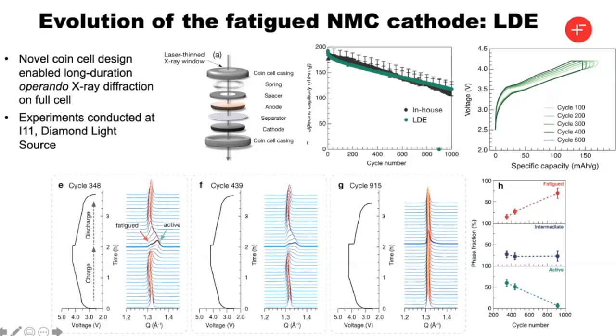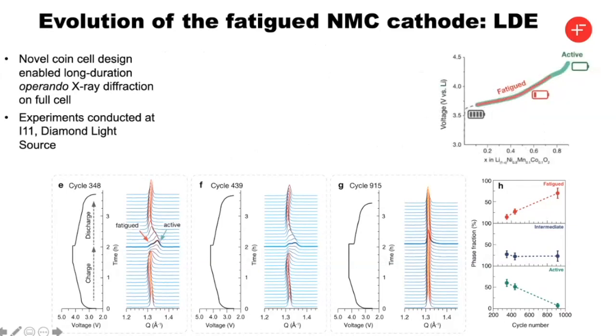And what you can see is as you progress from cycle, each sort of 100 cycles, we're getting increasingly more fatigued. And by the time we get to, say, cycle 915, there's no active phase left. The whole material is essentially all fatigued. So there's none of this collapse of the C parameter at the top of charge. So let's think about this a little bit more.